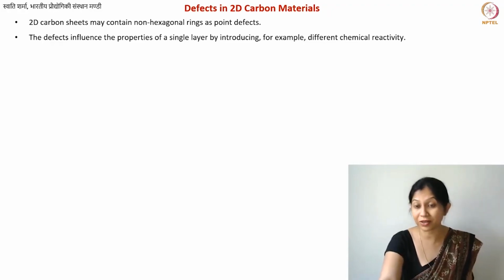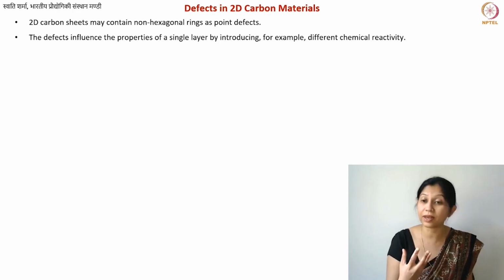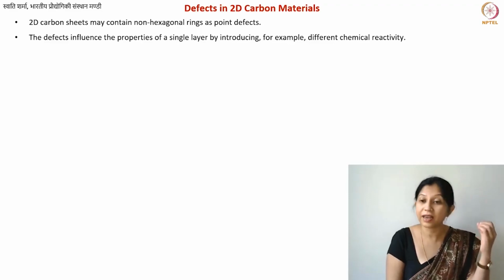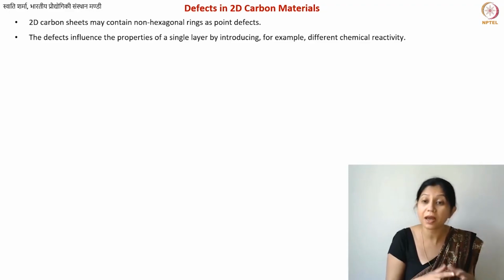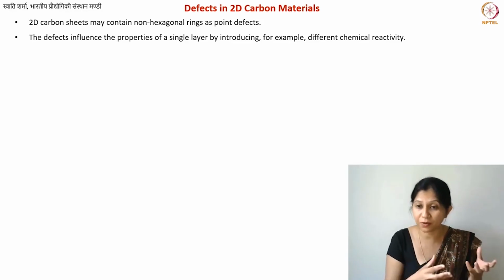One important thing is also that the defects definitely influence the properties of your graphene. Sometimes they introduce, in fact, new chemical reactivity. In principle, your graphene should be relatively inert. But if you have a certain, let's say, unpaired electron, a dangling bond somewhere in the middle, or if you have just nothing but a high energy structure, a structure which has a lot of strain, in that case, you may actually find that your graphene is more reactive compared to the one that does not contain them. So the defect-free graphene may not be as reactive.